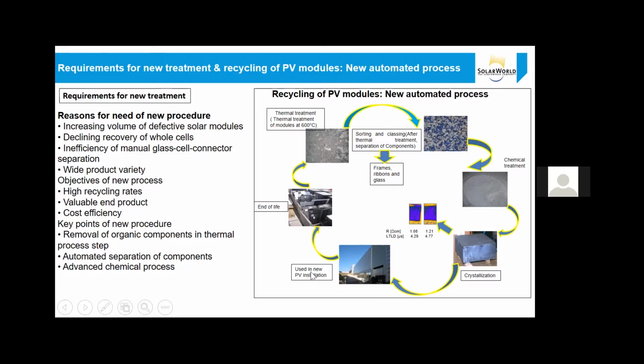We can see that a new solar photovoltaic installation breaks after the end of life, and they use thermal treatment, like 600 degrees centigrade in the oven. They separate it, and later use sorting and crushing after thermal treatment, separation of components. They melt it, and after melting use chemical treatment, and after chemical treatment make crystallization of silicon. So they showed it like that, and it can be used to produce a new solar photovoltaic module.